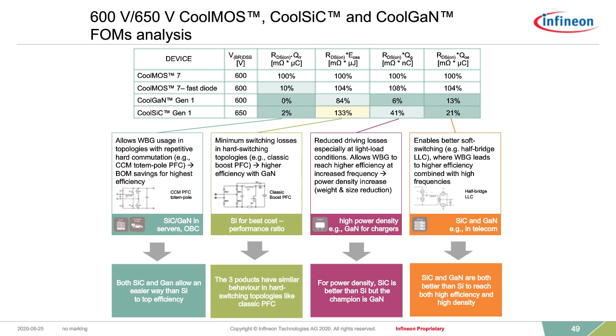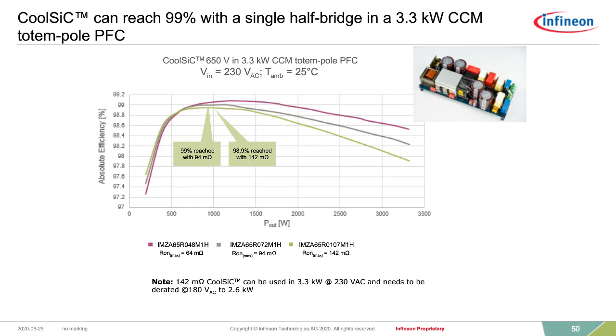Looking briefly into the application, this is a totem pole, a 3 kW board, basically, where you see that gallium nitride can be used, silicon carbide can be used. The key advantage of using silicon carbide in such a totem pole, where we typically see low switching frequencies, 40 to 60 kHz, somewhere in that range. These are applications where efficiency primarily counts. And here's the key advantage of silicon carbide: you can go with a relatively high RDS(on) and still manage in a single device to have a 3 kW PFC stage.